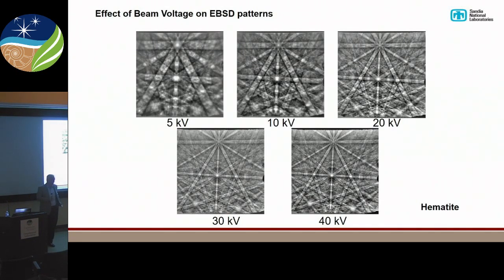And the same thing happens with tilt. Does anybody do TEM diffraction or has had any experience? A few. So when you tilt in the TEM, you have the rel-rods, right? And so you can tilt 5 degrees and your diffraction pattern doesn't change a whole lot, depending on how you do it. Here, as we move that sample even 1 degree, we can sense that change in orientation because the pattern is rigidly fixed to our sample. And so it's very sensitive to orientation.